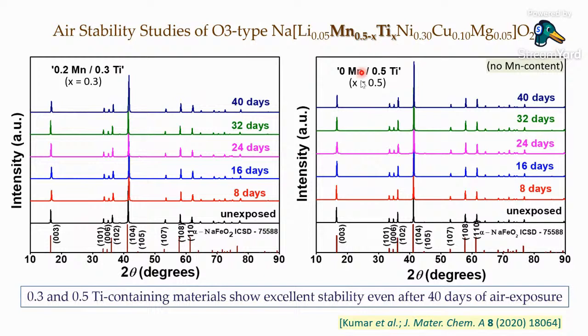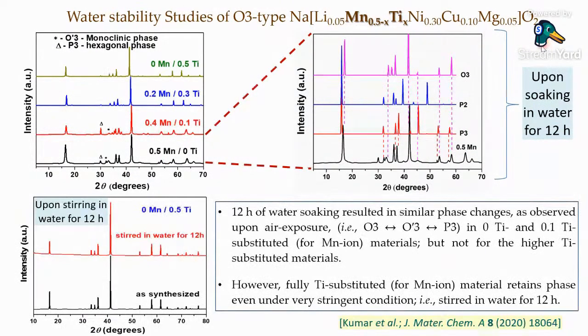So now we further started working with this 0.5 titanium containing material, because that was the most air stable O3 type structure that was probably reported till date. Now this is again seeing what happens when one puts it in water, a more hydrating condition, soaking and stirring. So we see that the 0.5 titanium containing material with 0 manganese is absolutely stable even if it is stirred in water for 12 hours, which is otherwise a highly hydrating condition. So this material is absolutely air as well as water stable. So it does not cause any problem with respect to synthesis and handling in air, because it is air stable, and in principle one can prepare electrode using water based slurry because it is water stable.